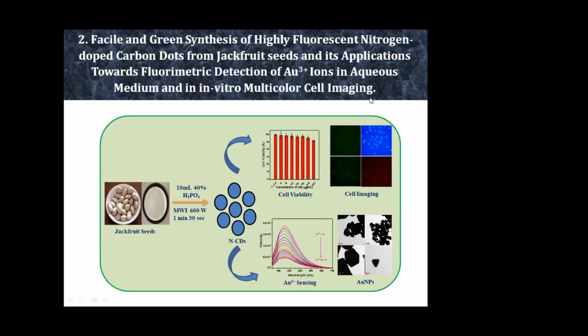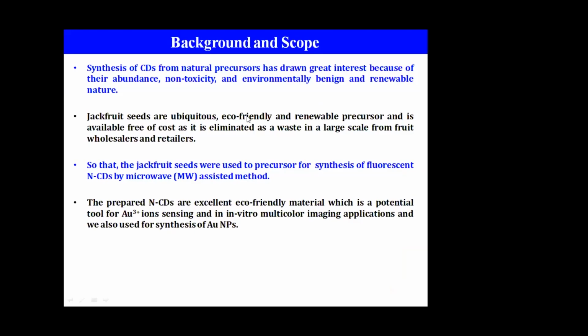Now, these jackfruit seeds—we took them and again used the method to synthesize in aqueous medium, and we could really see these fluorescent materials coming up. These CDs can again be used for imaging as well as sensing material. It's basically an environmentally benign and renewable natural source, which is a very important aspect. Jackfruit seeds were used, and a microwave method was used to synthesize this material.